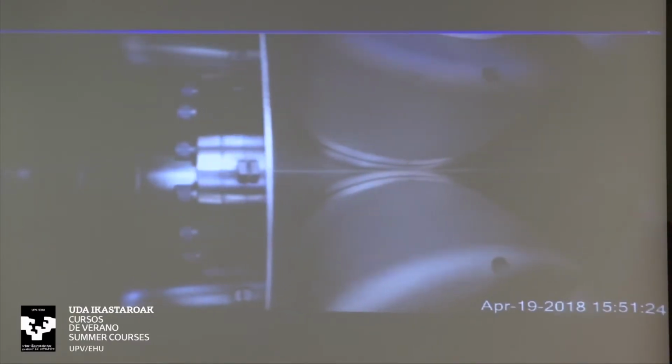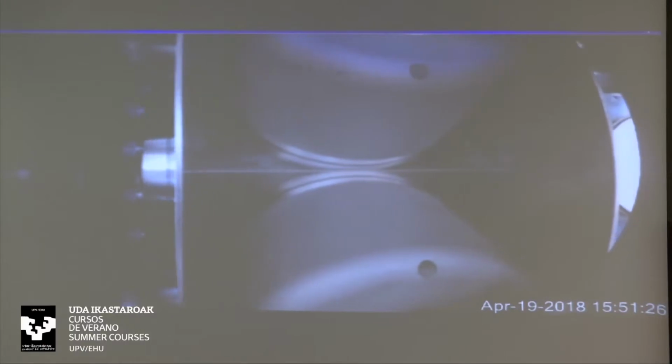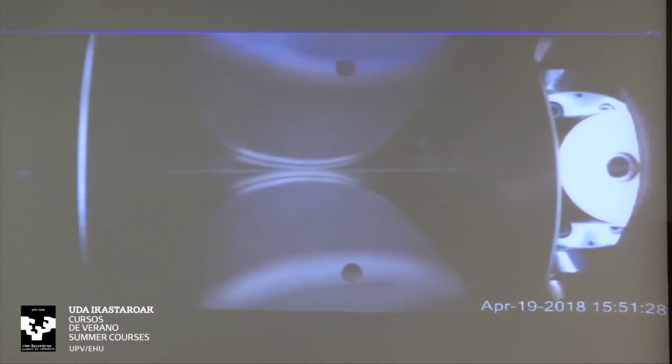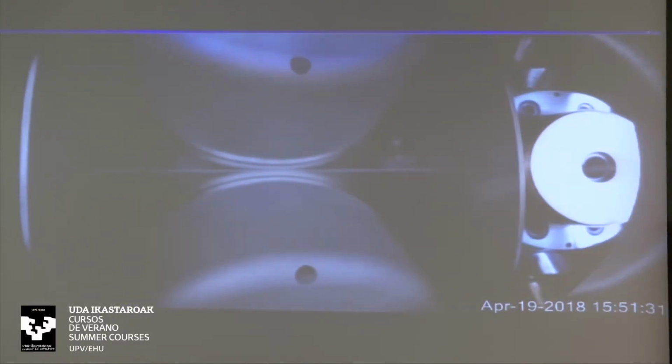This is a rather special part of the system. We actually have 12 magnetrons, which are these where we contain a material and which we use magnetic fields to locally create a plasma. And we have 12 magnetrons on like spokes on a wheel. So now you can see one of the 12 magnetrons, and then it will rotate to the deposition position actually, and then you'll see the plasma light, and this will be a target of magnesium oxide, which is a very important tunneling junction barrier material.